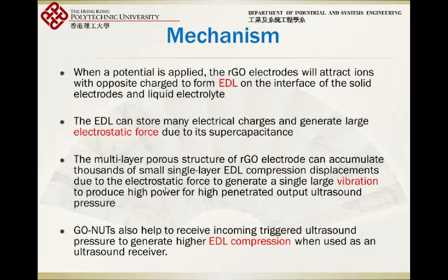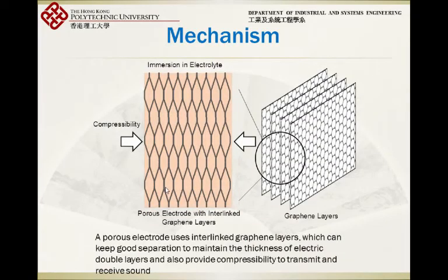I have already mentioned this part. If you want to understand more, you can search for EDL compression, and you can find the fundamentals of this. And actually, this was found a long time ago. So this is the graphene layers, and we try to make the porous structure of graphene layers. We use hundreds and thousands of these layers to accumulate this minimum displacement that can generate sound. And of course it can also receive sound to generate an electric signal.